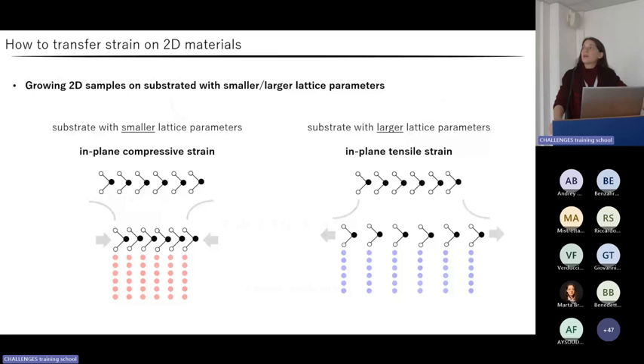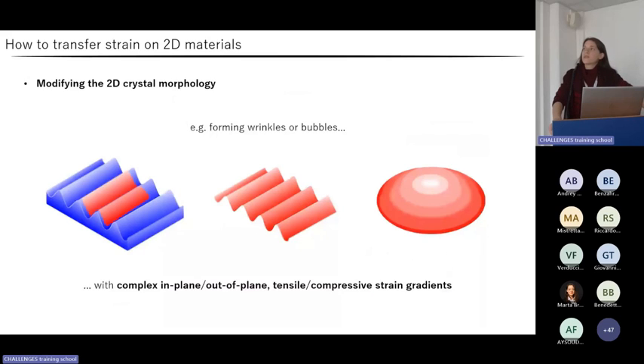Up to now, we have discussed techniques for strain transfer which are purely in-plane or out-of-plane. A pretty intuitive approach to achieve more complex strain gradients is directly modifying the crystal morphology to obtain, for example, wrinkles, bubbles, or waves with complex in-plane, out-of-plane, tensile and compressive strain components. In this case, I won't go into much detail because at the end of this lecture, we will discuss together a nice case study in which the sample under consideration is a monolayer with an unconventional shape. So we will see in that specific case how this exotic morphology is obtained and how the strain gradients are distributed across the surface of our sample.